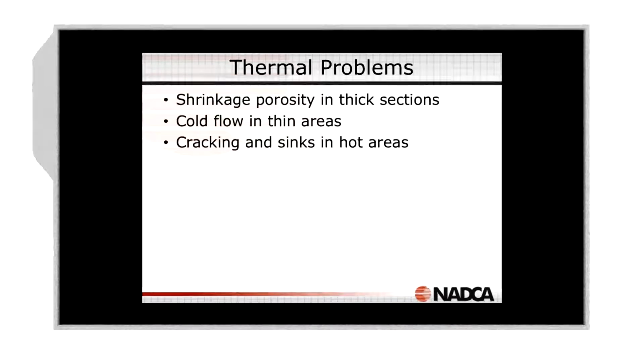Cracking and sinks in hot areas. Cracking is mostly a thermal problem. If one section is cooling faster than another, it wants to shrink. It will apply stress on other areas. If they are hot, then those areas will crack, because all molten metals, as they just freeze, have very little strength. I can take a screwdriver and push it through a casting just as it's frozen. So if it's sitting just below the solid temperature, I can push a screwdriver through the casting. It's very weak. Sinks in hot areas are just shrinks just near the surface.